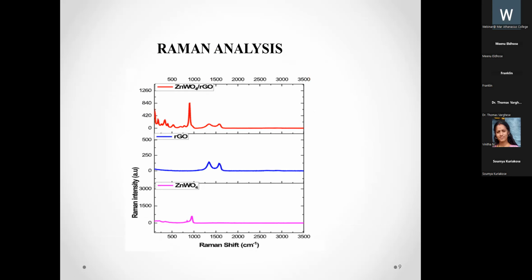This is the Raman analysis spectra which I have got for zinc tungstate, RGO, and the corresponding zinc tungstate RGO composite. It is more clear that the composite formation has been done. It is clear from this Raman analysis that zinc tungstate has only one peak, for RGO both the D and G bands are present, and for the zinc tungstate RGO composite both the zinc tungstate peak as well as the peaks of RGO were found here.